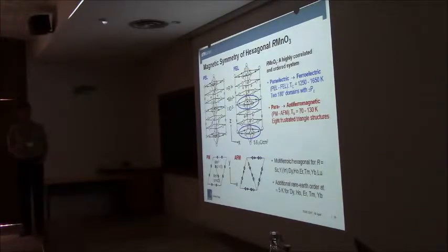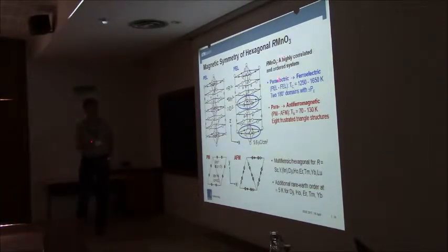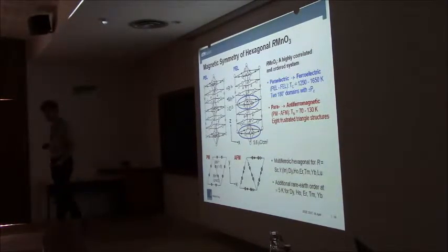Hexagonal manganites. So they have manganese with an oxygen bipyramid around the manganese. So 5 oxygen ions sitting around each manganese. Here you see these cages. And at a certain temperature these cages tilt. So you can see this ion, for instance, it tilts a little bit upwards. This one would tilt a little bit downwards. This one would tilt a little bit upwards. And these tilts and a couple of extra shifts, they make the material ferroelectric. Ferroelectric at between 1250 and 1650 Kelvin.